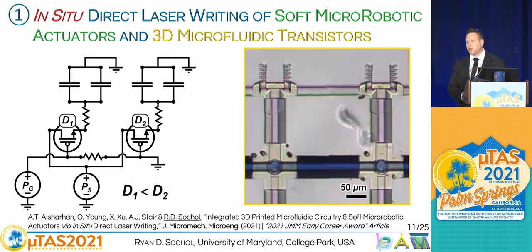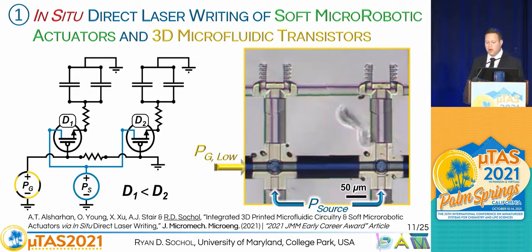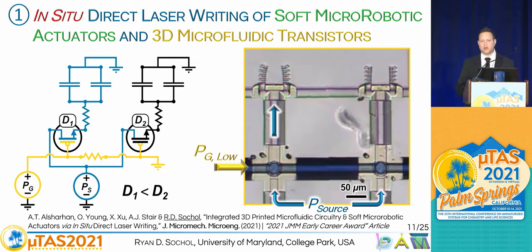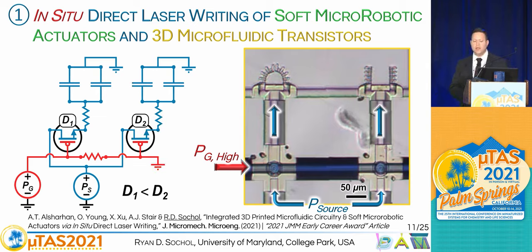And so what we're doing is we're applying a constant source pressure at the bottom to both that is identical. And we have these two different transistors where the only difference is the diameter of that sealing disk. And so under a low gate pressure, it's able to activate that very first transistor, but not the second. And as a result, only this very first set of microgrippers is able to close. But by increasing that gate pressure to a high pressure, now finally that second transistor is able to open, and you're able to then close that next set of microgrippers.